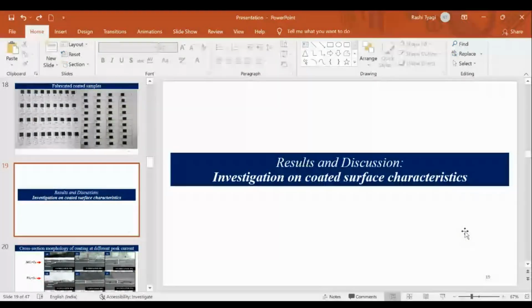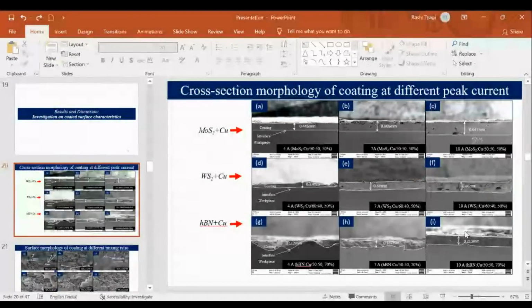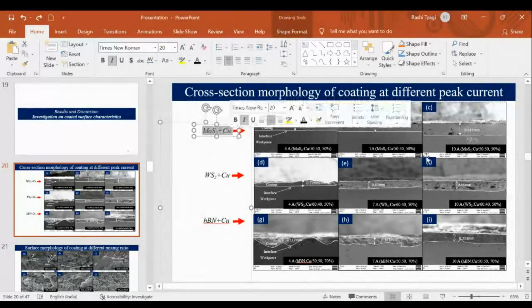So we'll discuss the investigation of coated surface characteristics. It means we understand how the coated surface characteristics change. So see, this is a cross-section morphology of the coating at different peak currents. It is observed that when the peak current increases, figures A to C show the cross-section morphology for MoS2 plus copper coating.